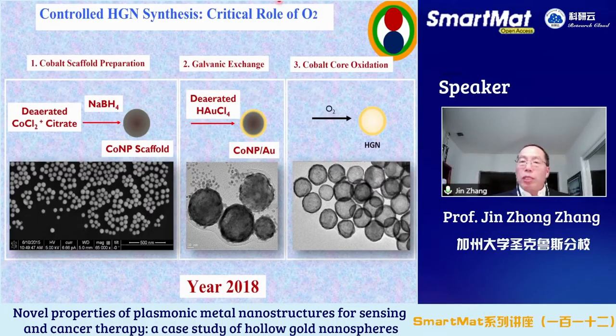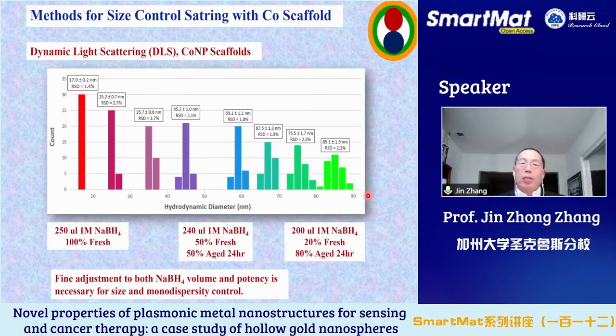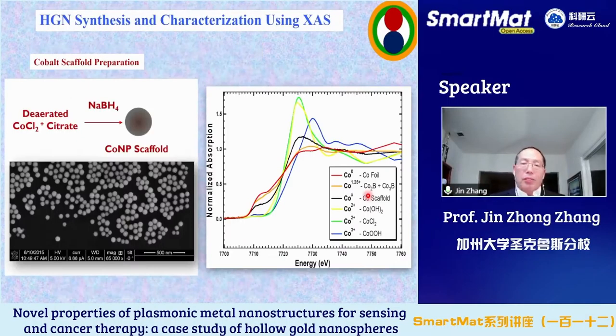It turns out we do know oxygen plays a role, but we don't know exactly what role oxygen is playing. So Sarah painstakingly spent 6 years in my lab to work out the mechanism of this reaction. I'll not give you all the details. This is published if you're interested. It's published in 2018. She decoupled the synthesis into many steps. As I show here, you can see this beautiful cobalt, very uniform, and this very uniform HGN after she worked out the mechanism. And there's a lot of details I'll not go into. We do EXAFS, we do a lot of detailed study. Sarah did, I should say.